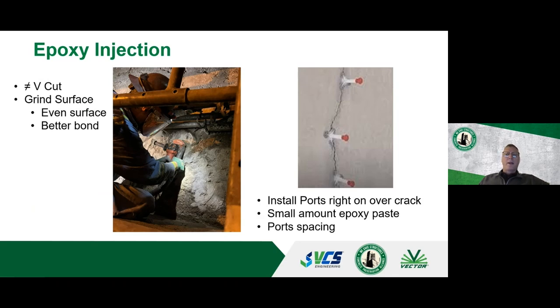Port spacing is determined by the thickness of the element you're trying to repair. So typically, if you have a 12-inch thick wall and you're trying to repair a crack, your spacing in your ports will be about 12 inches. Now, when I'm repairing a concrete base for a motor base, and that is 6 feet in thickness, well, I'm not going to put my ports 6 feet apart. So the general rule is, depending on the size and the width of the cracks, around 8 to 10 inches on your separation of those ports.